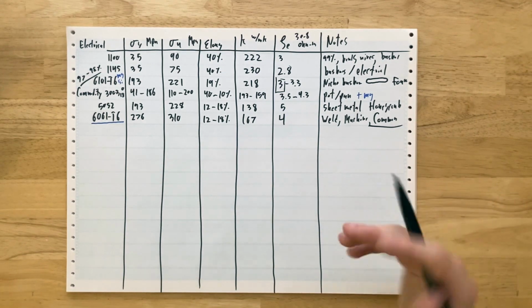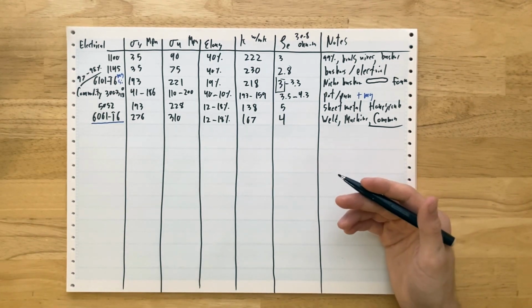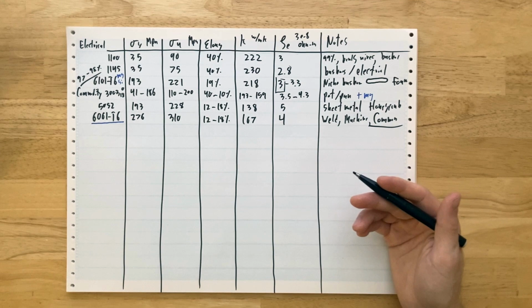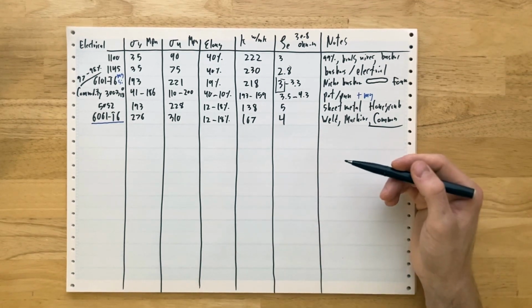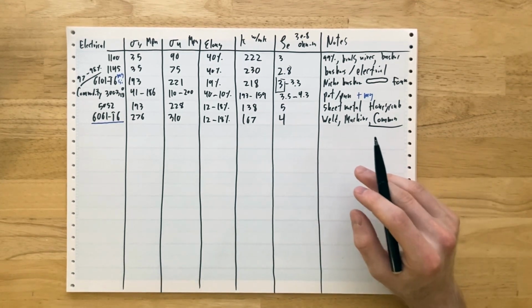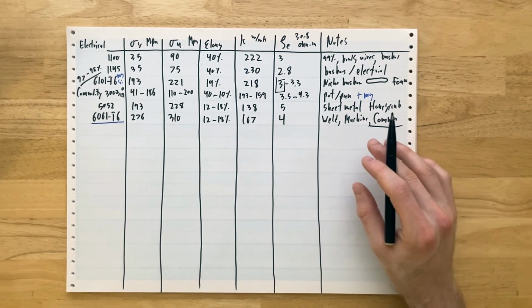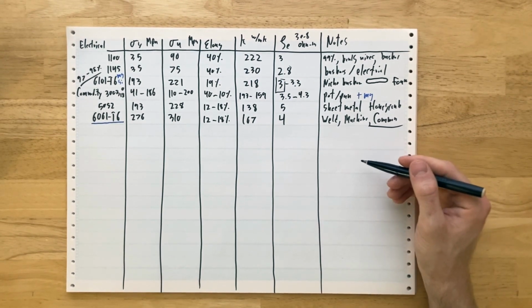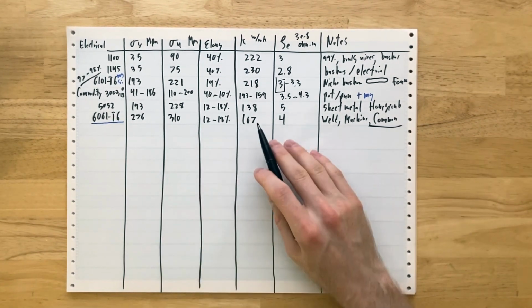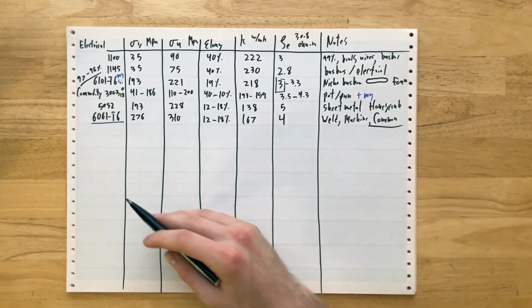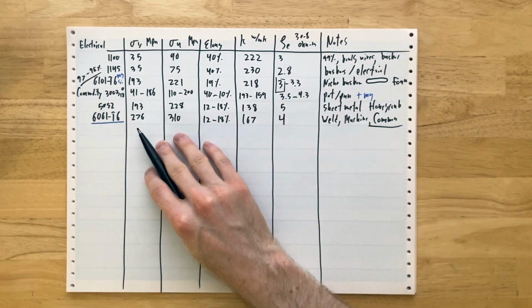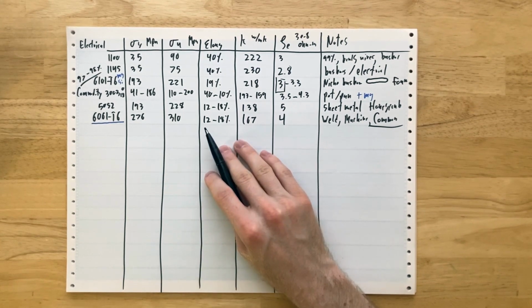It will distort things. You need to have careful fixturing, and you need to have a really big oven to do it in. So some people will weld it and not heat treat it. You just need to be really careful that that's going to be okay for your strength condition. And if you can't find a good table saying 6061 with this type of welding gets you this strength, assume you're going down to the T0 properties, your yield strength and ultimate strength fall enormously. So be careful there. Okay.